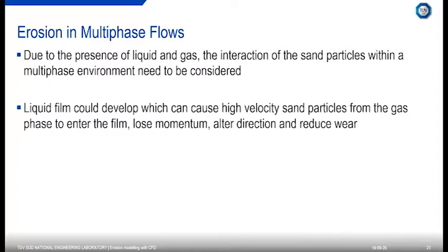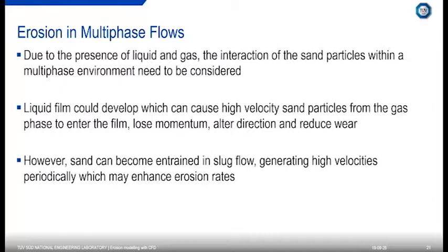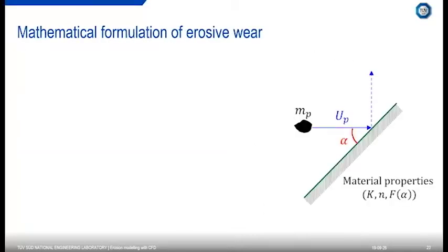We do have this example where we have this liquid film. This could develop, and it could cause these high-velocity sand particles that are within the gas to become trapped within a liquid film, lose momentum, possibly alter direction and reduce wear. However, if we have another flow regime, such as slug flow, we have periodic regions of high velocities, either at the front of the slug or perhaps within the gas, and these can periodically come in and actually enhance erosion rates compared to a single phase application. So it really does just depend on the flow regime, the particle size, the mass of particles, and the fluid velocities. So let's pop this into a nice mathematical formula.